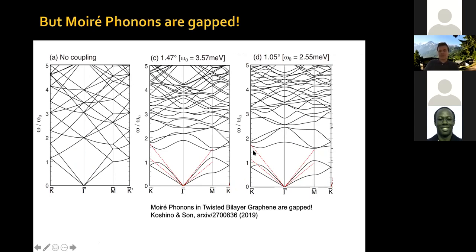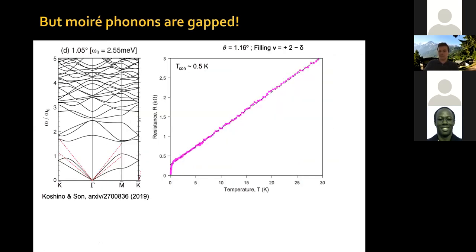It seems to be harder and harder to reconcile this linear in temperature resistivity behavior with any type of phonon system, okay? In particular, Moiré phonons will give you gaps, which will lead to differences in the slope of this linear resistivity behavior piecewise in different temperature ranges. But you can see that the slope doesn't change at all from close to 0 temperature all the way to temperatures above the Fermi temperature, okay? And that is extremely surprising. And that's, again, something which is typical of the strange metals in correlated materials.